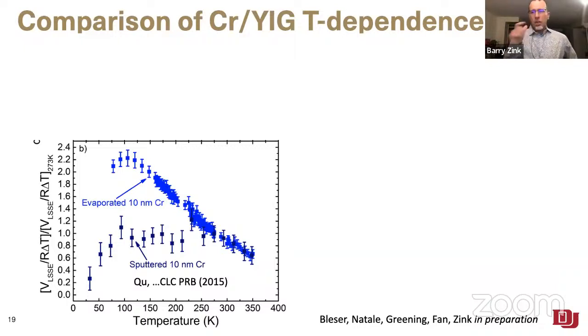So first, here's that same efficiency plot with just focusing on the chromium. And what we've done here is digitize the data from C.L. Chien's group's PRB back in 2015, the original inverse spin Hall effect work on chromium, and normalize it all so that we can compare the temperature dependencies. So what we see is that at high temperatures, our data agrees extremely well with the sputtered chromium that was measured by Chai-Ling several years ago now, but at low temperatures, something different is happening.